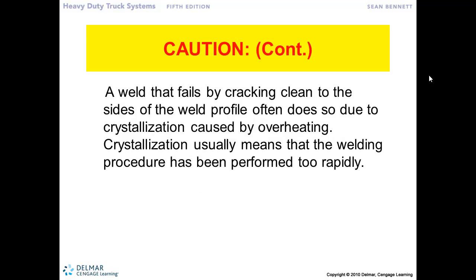The last thing we want is for that welded repair to be weaker than the surrounding material. If it was not done in a proper manner, we have weakened the material around the frame due to not heating or cooling the frame properly, and now we've crystallized the material around that weld. That becomes the weak part, and cracks start propagating from the material beside the weld.